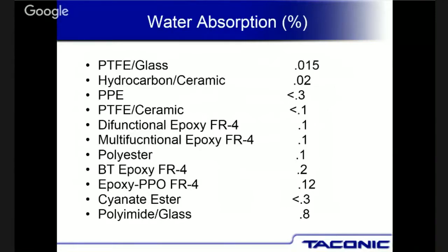But what's interesting is that water absorption is only one part of it, and it's on the data sheet. It says moisture absorption is whatever the number is, but there's no way to predict the chemical absorption. And some of these materials will pick up chemistries like you wouldn't believe. They won't pick up water, but they'll pick up the trichlor, all the different plating solutions. And I tell you what, we have a lot of issues in our industry when people are using materials and they don't properly rinse and bake the materials.